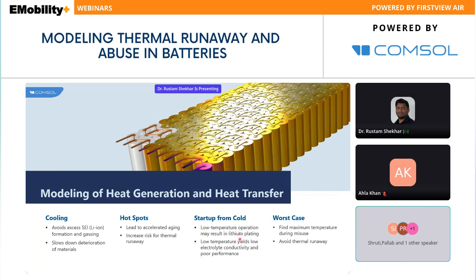So now you want to start the battery. We will be starting the battery from a very negative temperature, and from there we want to bring the battery to the optimum temperature where it performs well, which is 30 degrees to 40 degrees. So this startup from the cold environment is also one of the scenarios which we can see by adding heat transfer to the battery modeling. So the startup scenario, hotspot formation, and cooling, all three can be possible operational conditions.